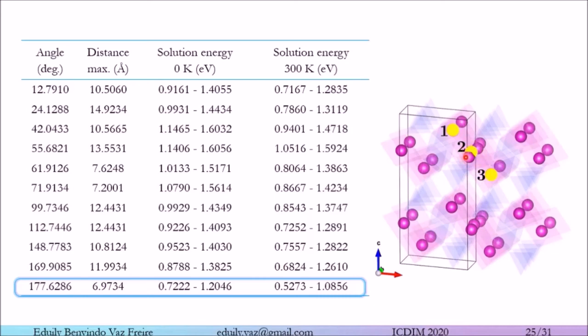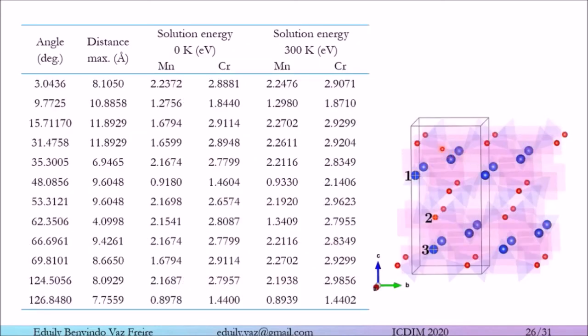For transition metals, we have the same trends as before, changing the ions involved in this configuration. The least energetic defect is at the dihedral angle of approximately 127 degrees, and the distance continues at approximately 7 angstroms. In the picture, we can see the configuration between the ions involved in the formation of the defects. This point in yellow. Okay.